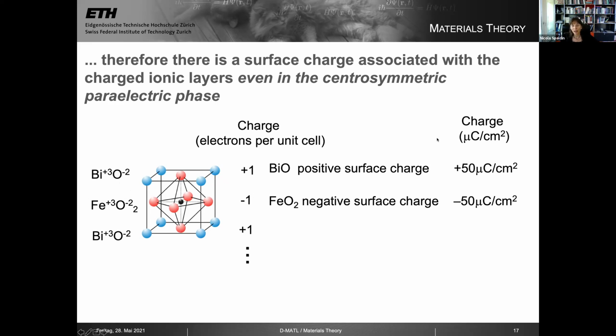And if I work out the values of these surface charges in ferroelectric units, what I find is that the surface charge associated with the bismuth oxygen surface is plus 50 microcoulombs per square centimeter, and the surface charge associated with the FeO2 surface is minus 50 microcoulombs per square centimeter. That's if I convert 1 electron per unit cell into ferroelectric units.